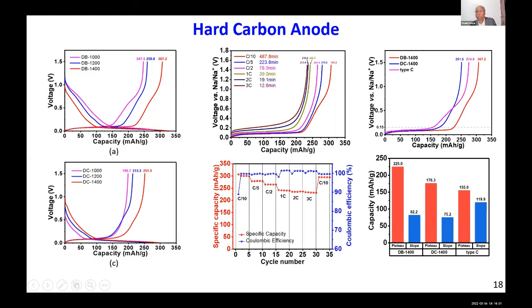Most importantly, you must look at this plateau. You look at the plateau and the slopey region. You see here, the plateau is longer and the slopey region is shorter. That's very important. The plateau is the one which is going to give you the difference of the cathode and the anode potential and the actual potential of the full cell. So the plateau has to be longer, and that is something which we are able to achieve with the help of our material, so-called DB 1400 degrees centigrade.